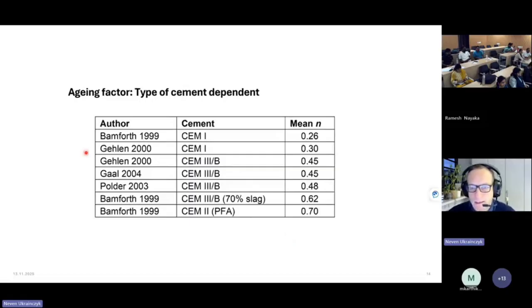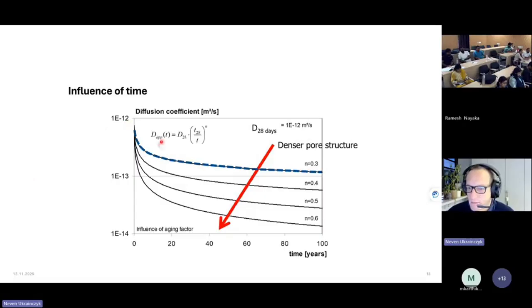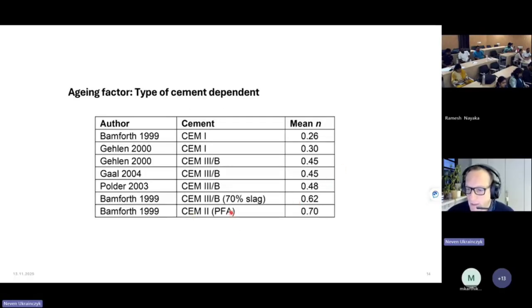So there are some aging factors depending on the type of cement. CEM I would have 0.26, so very fast, there is no big change between 28 days and the final. But if you use fly ash, you have a very big aging factor coefficient, 0.7.